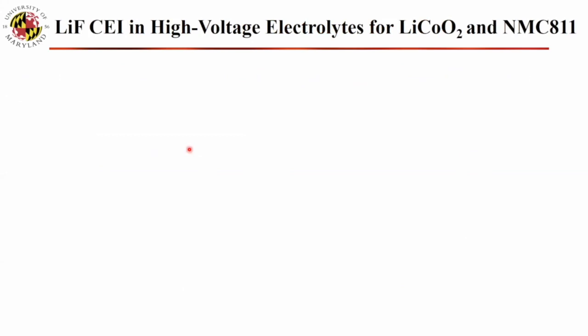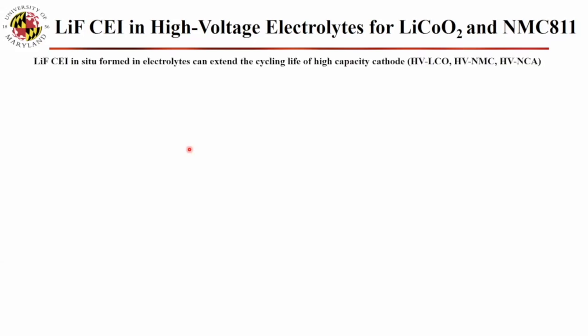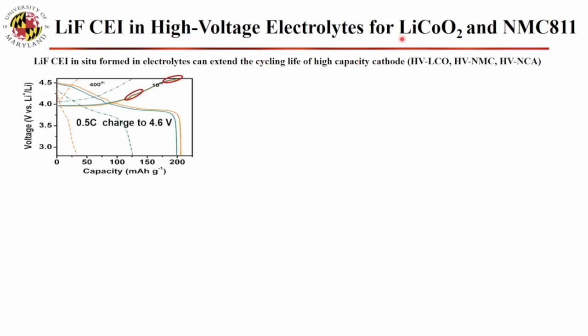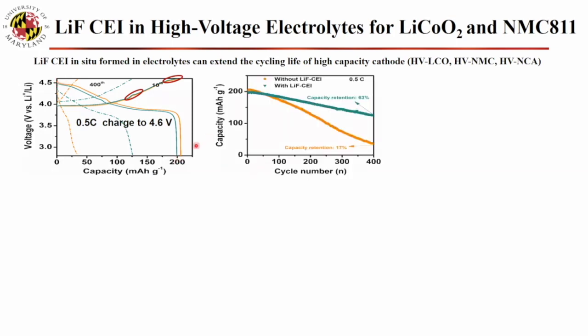So we demonstrate, we say this is universal, not only for anode, any high capacity electrode, this should be suitable. And then we check the cathode. Lithium cobalt oxide, if we increase the charge potential to 4.6, we can get high capacity, 200. But a traditional electrolyte quickly decays.